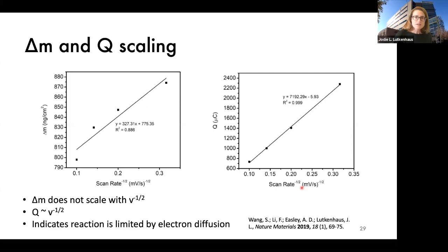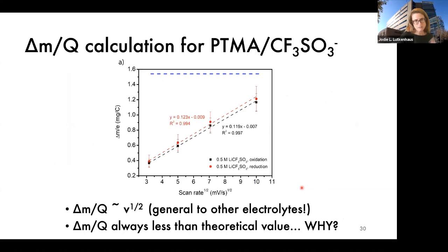Okay, so we're taking the plot on the left and the plot on the right, and we're dividing delta M over Q, and now we're plotting it by scan rate to the 1/2 because Q is now in the denominator. So our results are linear. Delta M over Q is linear with scan rate. We've also seen this general to other electrolytes, I mean, other salts. And then here, what we wrestled with for a few months was that the delta M over Q value is always less than the theoretical value. And it was really hard to get around that.